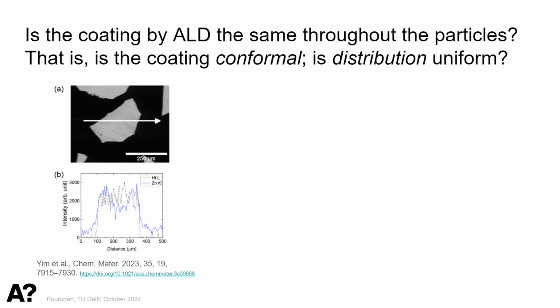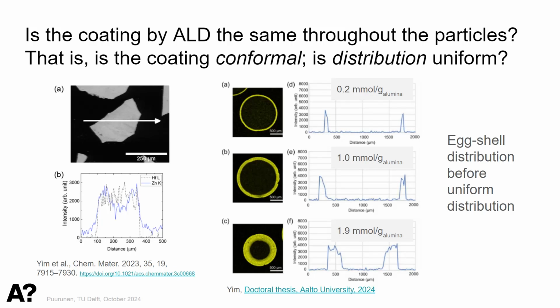Then, continuing from this, is the distribution uniform? Is the coating the same everywhere? Here we observe that little dip. We then made experiments on totally other particles, spherical alumina, and we varied the dose that we deliver in the fixed bed. And here you can see that, first of all, no, it's not always uniform, not at all.